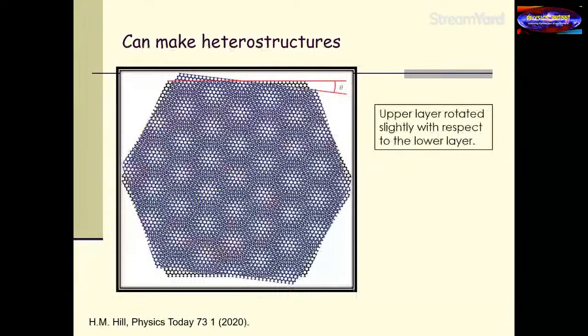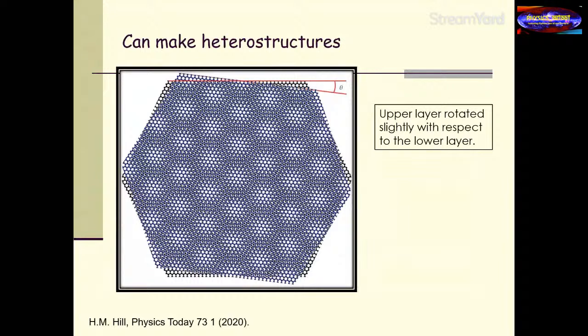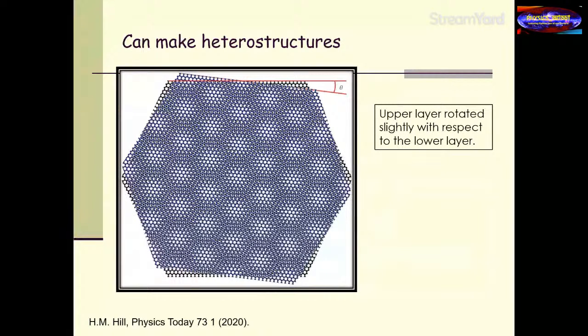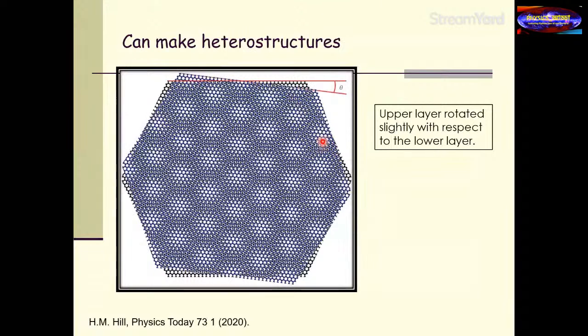Okay, so now what I can do is, as I said, in contrast to normal semiconductor epitaxy of covalent materials, where I have to make sure that whatever atom I add usually likes to sit on top of an atom of the lower layer. If I'm trying to grow two different materials, the lower layer is imposing its lattice constant on whatever I grow on top. Whereas in this case, we can do something more unique. If you took one layer, and what is shown over here is the unit cell corresponding to one layer, and then I put another layer, again the same unit cell, but slightly rotated with respect to the lower layer, I can make these kinds of heterostructures.